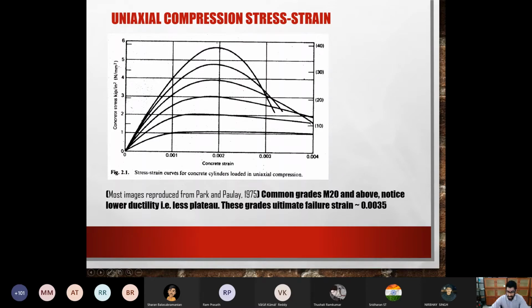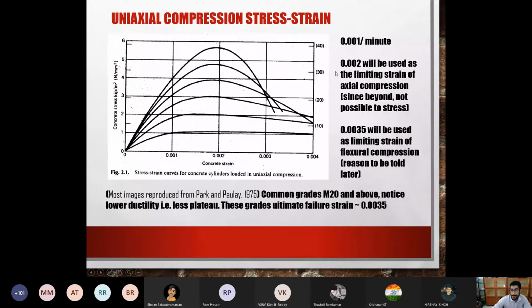So this is the point where you say that the ultimate failure strain of concrete in flexural compression is 0.0035. Of course, these low grade concretes do not end at 0.0035, but we do not use strain beyond that. We make a common strain for flexural compression. These are the conditions for getting these curves: it should be loaded at a strain rate of 0.001 per minute. 0.002 is the limiting strain of axial compression, and the reason is you cannot increase the stress beyond this, because at this strain the stress has reached its maximum. If you try to increase the strain, the stress is only going to reduce. 0.0035 we use as the limiting strain for flexural compression. The reason will be told later.